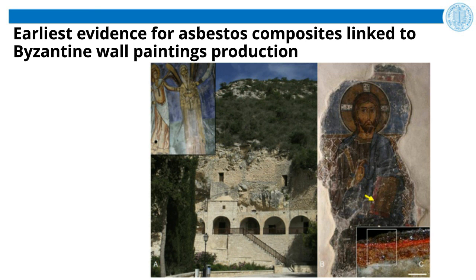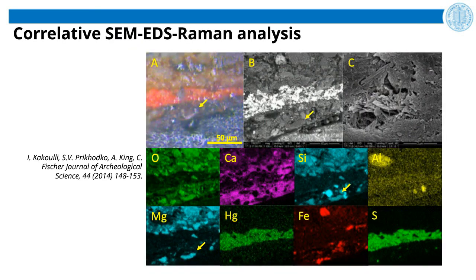On this slide, we can see the polished fragment of the paint sample with the plaster layer. A is an optical microscope image. On B, we can see a backscattered electron image of the same area as shown on A. And on C, we can see a secondary electron, high magnification image of an inclusion, which is marked with an arrow on images A and B. The same inclusion can also be identified on the EDS maps shown on the two lower panels.